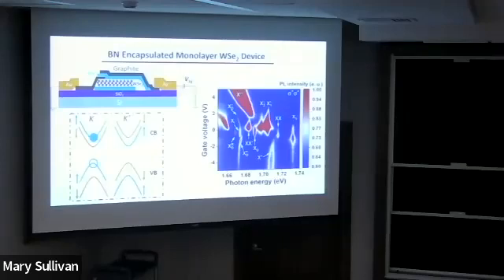So that's the goal. If you don't have a clean sample, what you see is a big blob here. You won't see all these fine structures. So this is exciton. That's well known. What's exciton? We said the bright exciton is one electron here and one hole here. This one here, X plus, corresponds to a P doping side. You add a free hole in the system. Because of the Pauli exclusion principle, the hole can only be here. So it forms a 3-particle state we call P trion or positive trion.